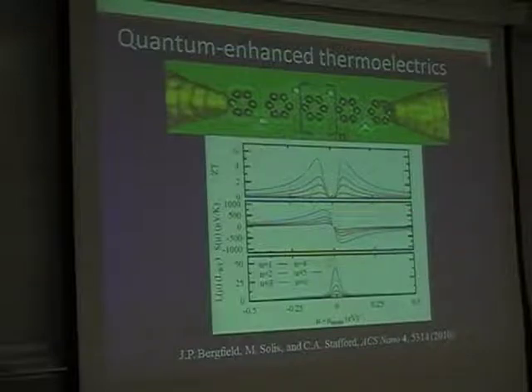And in a system very similar to this, indeed, we see that we can get a very large, very efficient thermoelectric engine. So here is a polyphenyl ether molecule, where this central block is repeated n times. And you see for n equals 6, we get a ZT up to about 7 and a thermopower of about 1,000 microvolts per Kelvin. So this would be a lot better than current technology. Now the question is, is there some connection between the way that the wave mechanics is controlling the motion of the electrons here and the fact that you're getting such large values of ZT? Well, to be able to meaningfully pose a question like that, you have to be able to look at what is happening microscopically within this system as the heat and charge are flowing to see what's really going on.